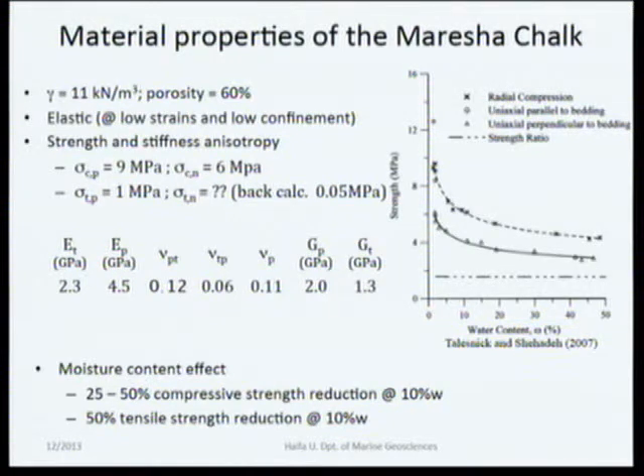Another thing that we have to remember, which is not written here, is that all of these tests that were done to determine these constants are done on very small samples. Some of them are as small as 50 millimeters, cylinders of 10 centimeter length, not more than that. If you enlarge the scale of the sample, you will get even lower values for strength. And if you take into account scale and environmental impact, the nominal strength of the rock is very, very low. It's not what is written here, but okay, for our purposes, it's more than enough. And we shall see it shortly.